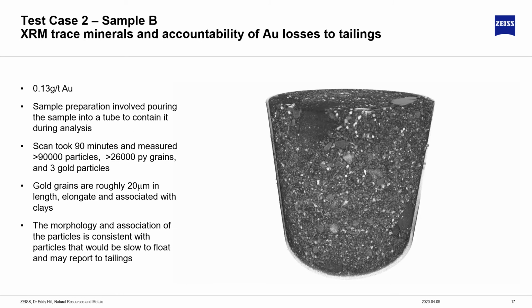Look at sample B. Here we're looking at 0.13 grams per ton gold. The sample preparation for XRM is a non-mechanical preparation. We simply pour the ground sample into a tube to contain it during the analysis. The scan took 90 minutes and measured over 90,000 particles in 3 dimensions. We have entire volume and phase recognition. Over 26,000 particles of pyrite and 3 gold particles in the tailings.